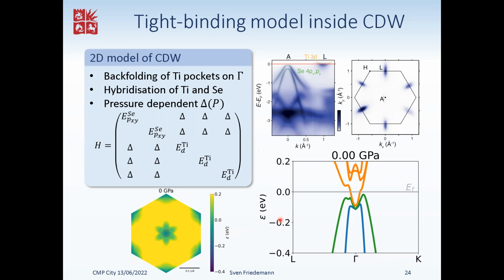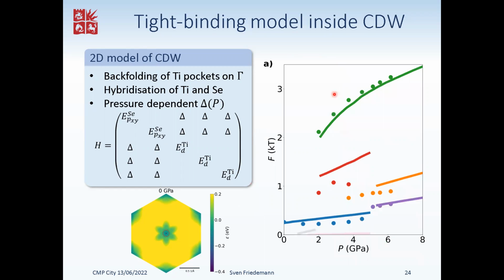And here you can see how the hybridization acts. So we've had 2 clear hole bands, which now hybridize with these 3 copies of the electron band, all shifted to the gamma point, but rotated to each other. So we have considered these to be elliptical with two axes of the electron mass, and rotated to give us this flower shape here.